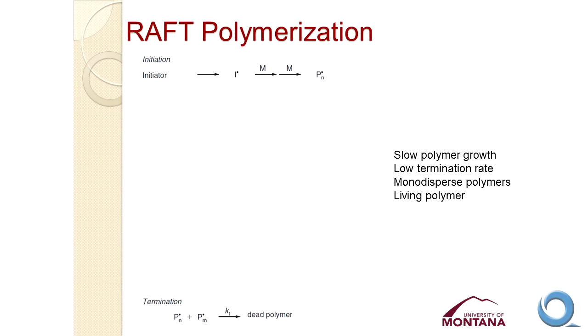These polymers are block copolymers, and they're synthesized by a specific type of polymerization known as reversible addition-fragmentation chain transfer polymerization. It's a free radical polymerization mechanism, but it's one that allows us to really control the structure and the size of the polymers very carefully. So on this slide right now, all we're seeing is just the standard free radical polymerization mechanism.